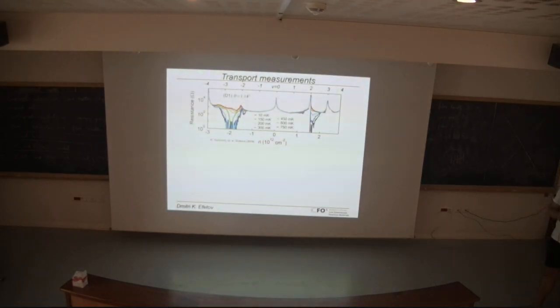So this is now transport data. Okay, so now finally I actually show some data. This is transport data from the Columbia group, which published this paper early this year. And what we now measure in these devices is just resistance. We just measure the resistance of the device as a function of carrier density. And usually what we observe is the following.